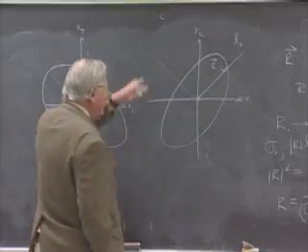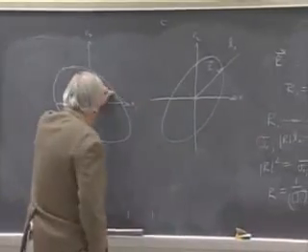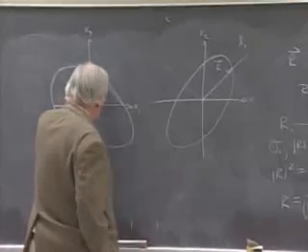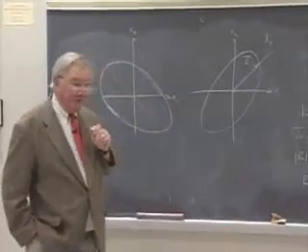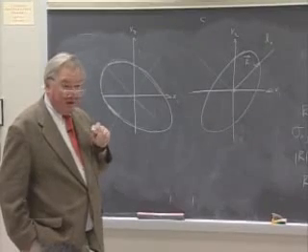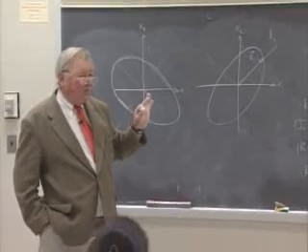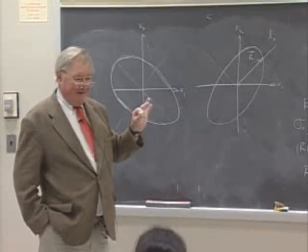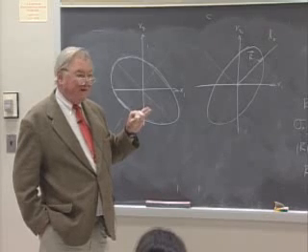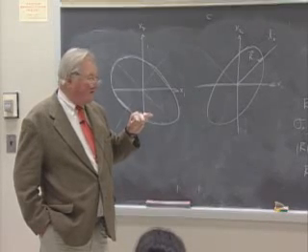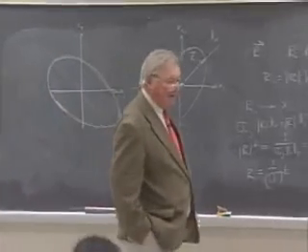It's going to go as the inverse square of the radii in the ellipsoid. But it is something that varies uniformly between extreme values of the maximum and minimum value of the property. We are, I assure you, for higher rank tensor properties, going to look at some absolutely wild surfaces with lobes and extreme values and very irregular variation of properties with direction, but not for second rank tensor properties.